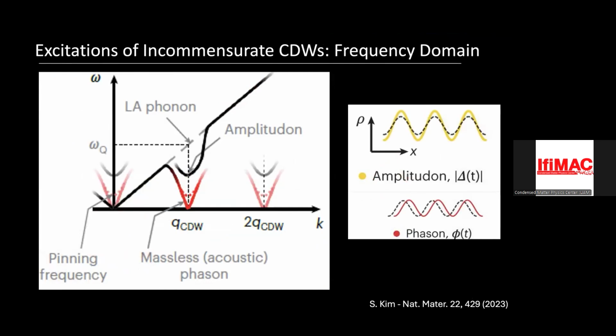Now that's in the time domain. In the frequency domain, what does this look like? When you enter into this charge density wave phase, this is the frequency and this is momentum. Okay. So what I've drawn here is one of the phonons of the system. This is the longitudinal acoustic phonon. Above the CDW transition, you just have some acoustic phonon in the system. This phonon is a lattice vibration, right? Now, if you go below the charge density wave transition, at the Q of the charge density wave, this thing softens, and the amplitude and the phase mode look like this. So this is the dispersion of the phase mode. The fact that it looks like this and goes to zero, the frequency can go to zero, tells you that the phase mode is massless.